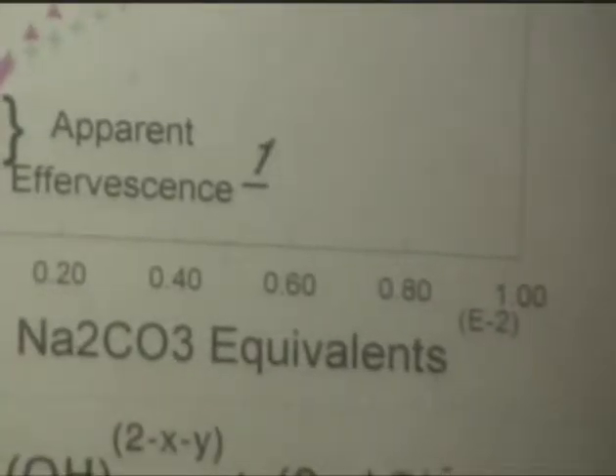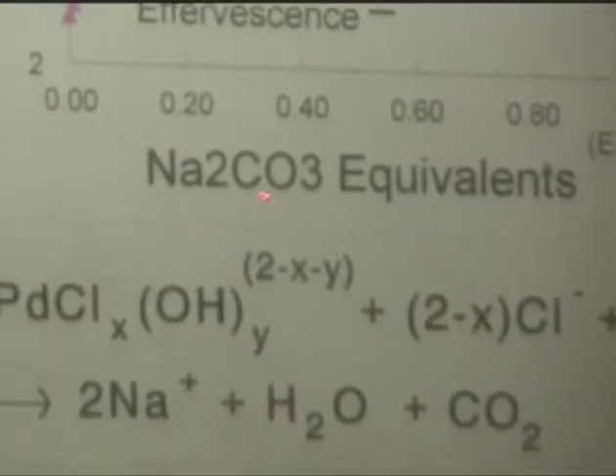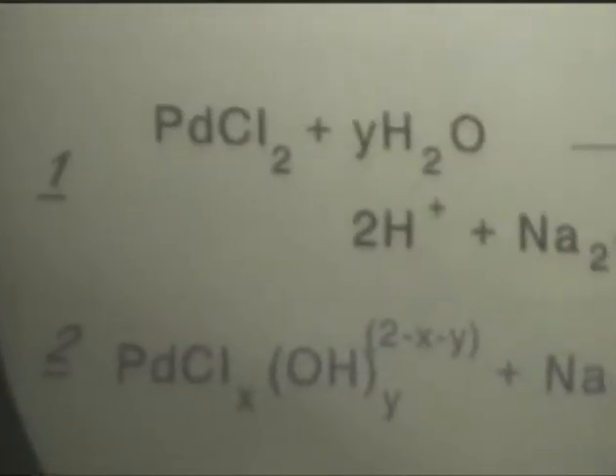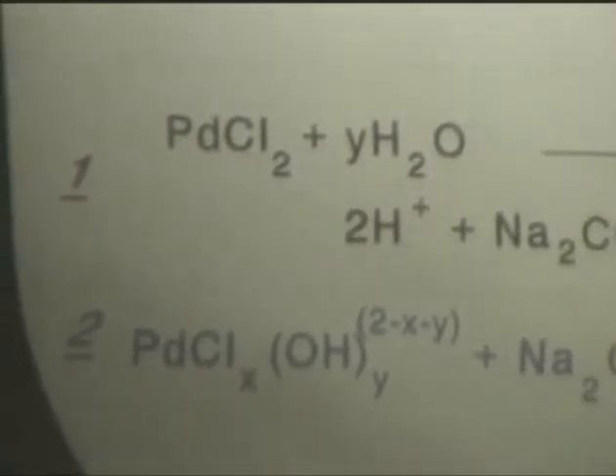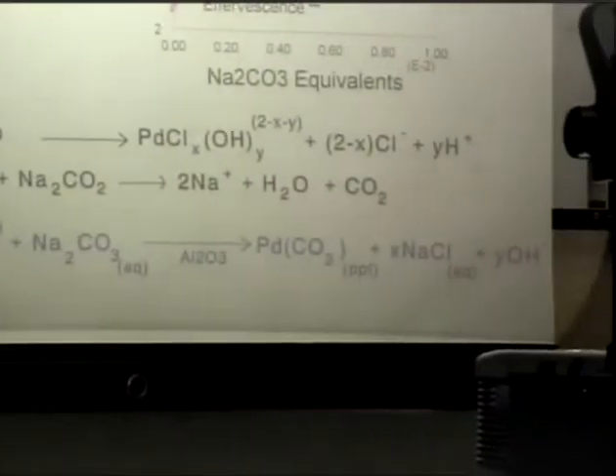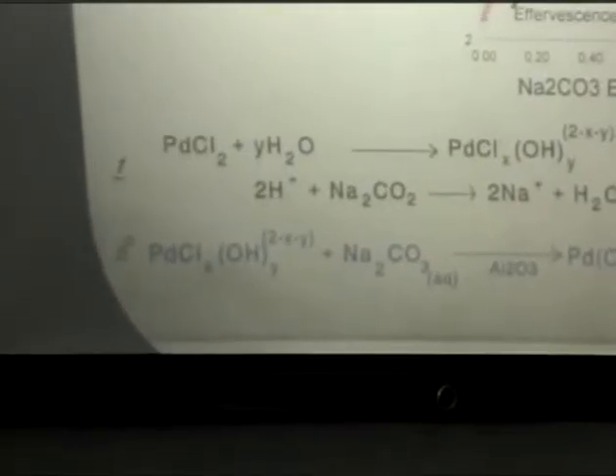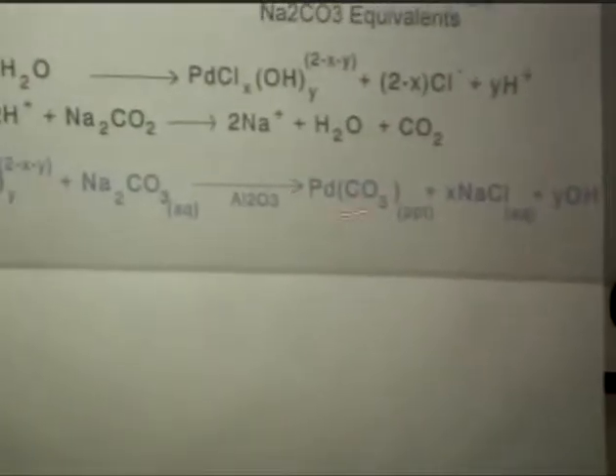And so we started, and the first thing we started with was something very simple: a simple titration. Aqueous phase titration using the metals as the acids in this case, and titrating with sodium carbonate. What you would expect, again, if you would precipitate the hydroxide, is that you would make some CO2, and you would see some effervescence. It would bubble. But on the other hand, if you would make the carbonate, and I hope you all can see that, you wouldn't see the effervescence. Essentially, you would deposit the carbonate, and the CO2, instead of bubbling, would be in the solid.